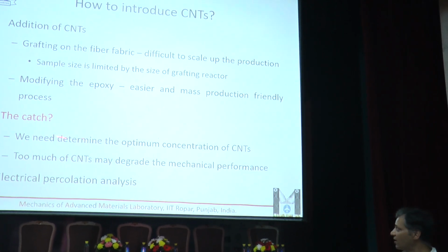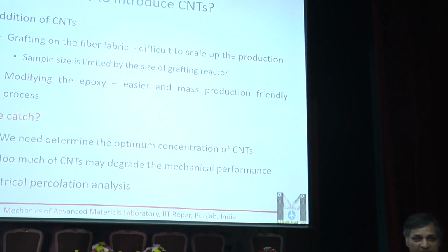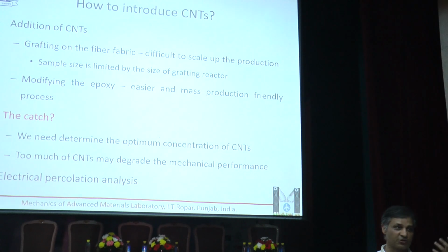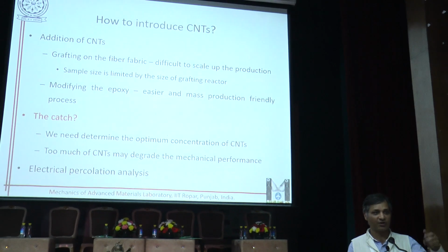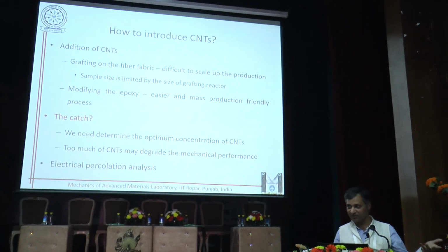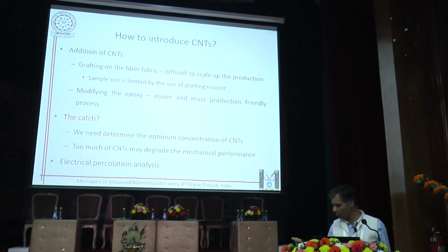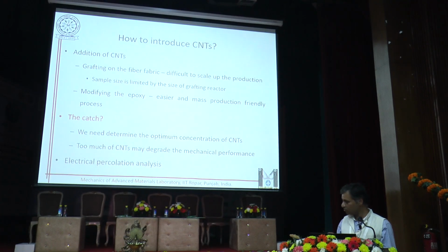Now the catch here is that we need to determine the optimum concentration. How much CNT to be used? What is the right amount of CNT? Because if you use too much, there are other consequences. For example, the viscosity of the resin will be too high. You cannot process the composite using the composite processing techniques, right? So those challenges will come. So that's what we determined using electrical percolation analysis.